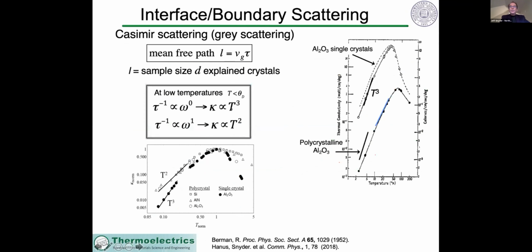Okay, so another thing that we think is new and interesting in thermal conductivity has to do with interfaces and boundaries. And just as a reminder, at low temperature for single crystals, we know that the thermal conductivity behaves like T cubed, which can be explained by scattering from the size of the crystal itself.